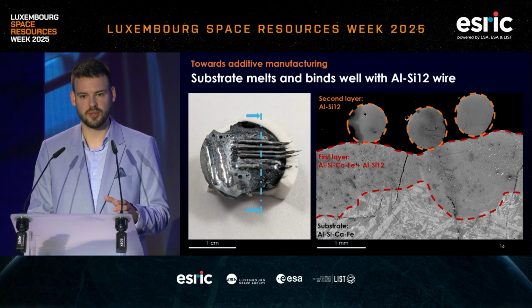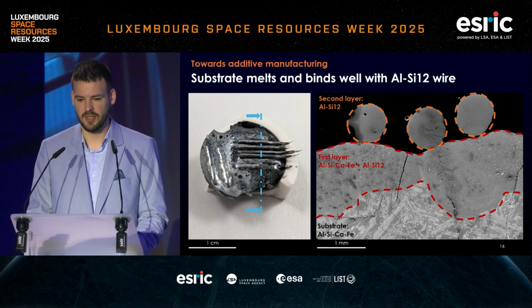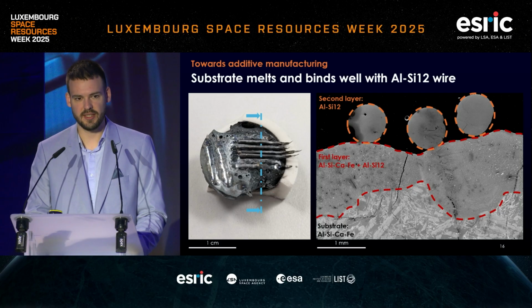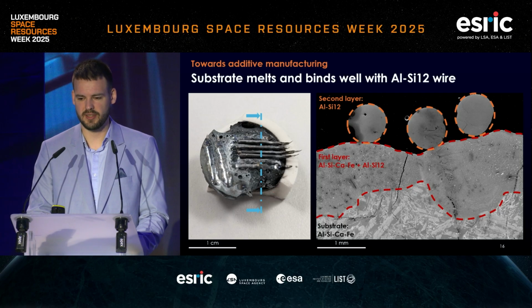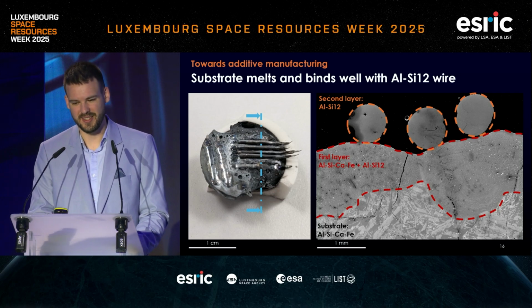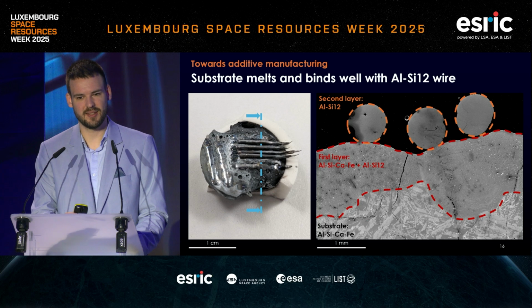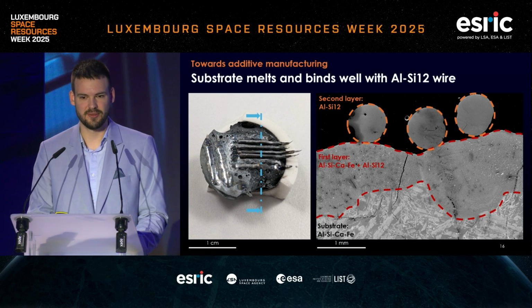On the bottom, you have the substrate, which is very similar to the ingot I showed earlier. And then the interesting part is the first layer is very well mixed between the aluminum alloy and the substrate, with very good adherence and kind of mixing of the material. And when you look at the second layer, we can actually see that the metal wire we're depositing adheres less well to itself than it adheres to the substrate. So that's quite an interesting result for us, showing that the material does have potential for additive manufacturing.